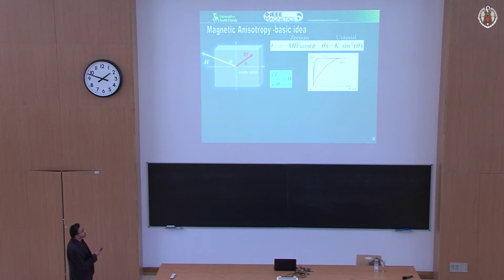I am a physicist like many of you, so I have to show at least one equation in my slide. So this is my equation slide. It's a very basic equation. All it tells you is that at high fields, this term, the Zeeman energy dominates, and so you have saturation. You're forcing the magnetization to align in the direction of the field. And at low fields, the internal energy, which is captured by this so-called anisotropy, is going to determine which direction your magnetization vector is pointing. That's all there is to it. So it's a competition between these 2 energies that determines the shape of the hysteresis loop.